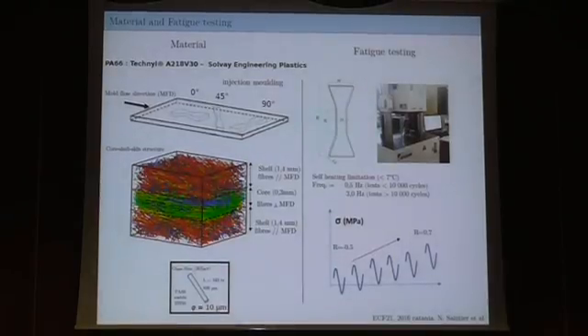The material we are looking at is short fiber reinforced polymers that is obtained by injection molding. So we obtain plates, and we extract from these plates some specimens which are this shape and at different angles, which is classical if you want to evaluate the effect of anisotropy. And if you look at the microstructures in the thickness, you will obtain such microstructure.